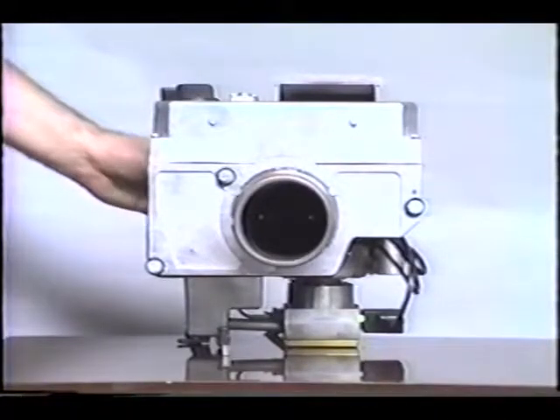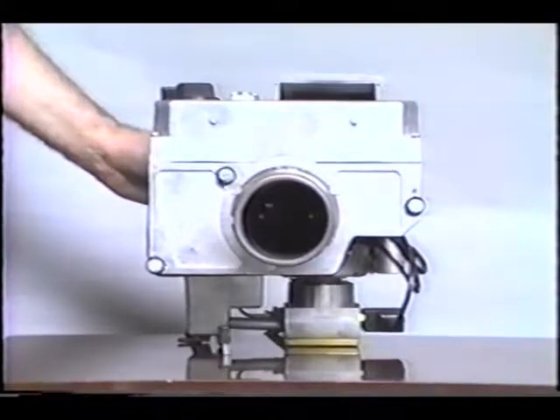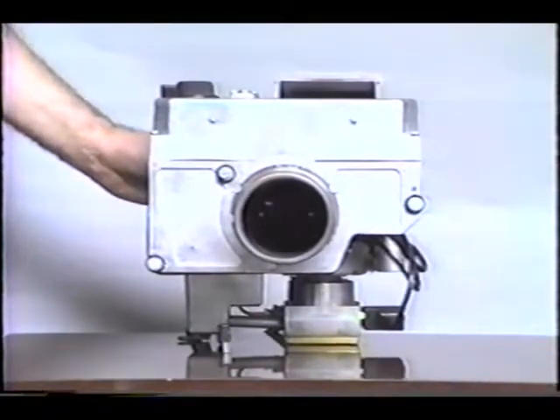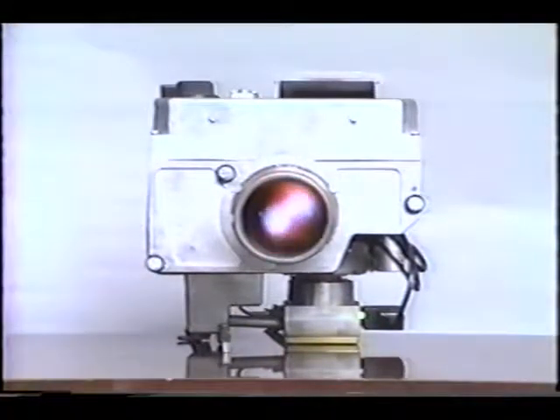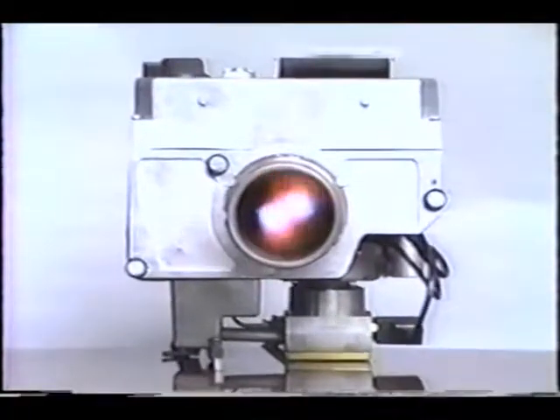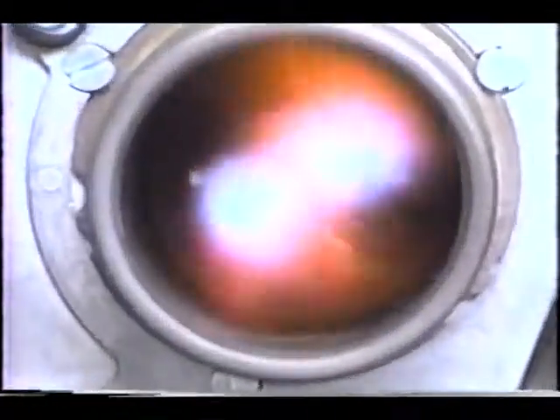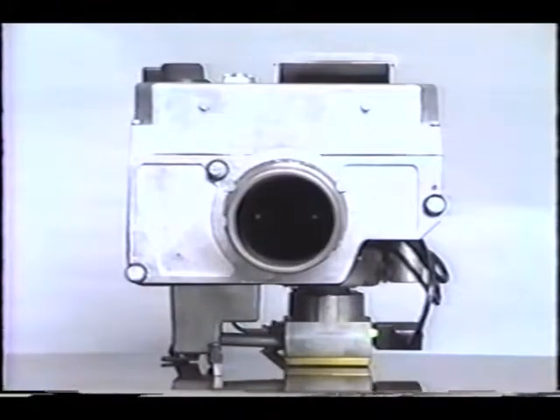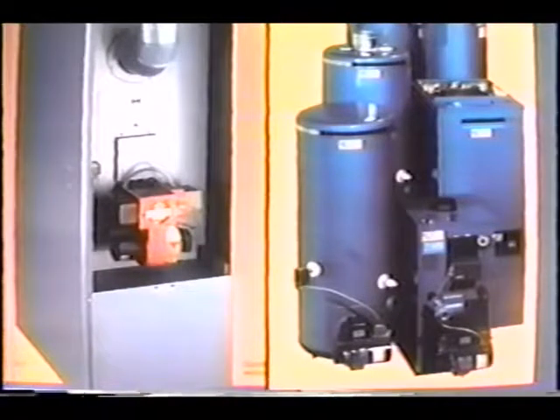Even at its lowest firing rate of 0.2 of a gallon per hour, a condition conventional burners cannot approach, the Airtronic burner will cleanly and efficiently burn high viscosity oil, even at very low temperatures. For example, the U.S. Army recently operated the Airtronic burner at 53 degrees below zero, using a winter-grade diesel fuel. These tests were conducted following a 24-hour cold soak of the burner at the same low temperature.